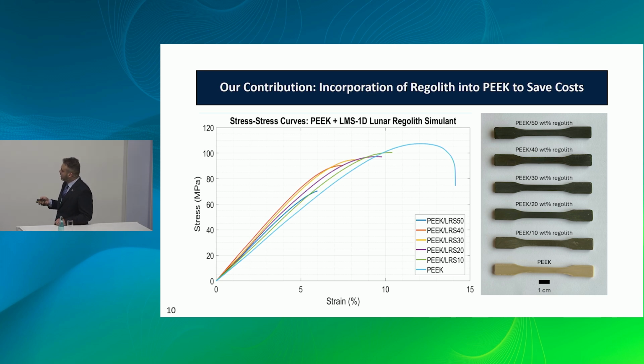In the tensile strength curves, PEEK stands on top in terms of ultimate strength, but as we add more regolith particles, we reduce the mechanical performance, though it's not huge, up to 40%. But for 50%, there's a drastic decrease in the mechanical strength. Also, as expected, as we add more solid material to the composite, we reduce the maximum elongation it can reach. The stiffness increases by adding regolith particles, but for 50% it decreases again because of defects imposed by the high melt viscosity of the composite, which makes the extruding more challenging.